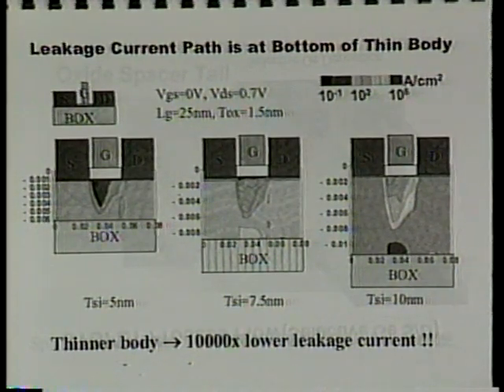So you see the worst place for leakage is far away from the oxide, which is not surprising if you just think about what I just explained earlier. So don't think that the current always flows along the surface. It's not surprising that it cannot flow there, because the oxide is preventing the barrier from being lowered, but nothing is preventing it from being lowered here. So how do you deal with it? How about just cut this part out? Yes, cut the part out, leakage reduced by orders of magnitude, but still the worst place is here.